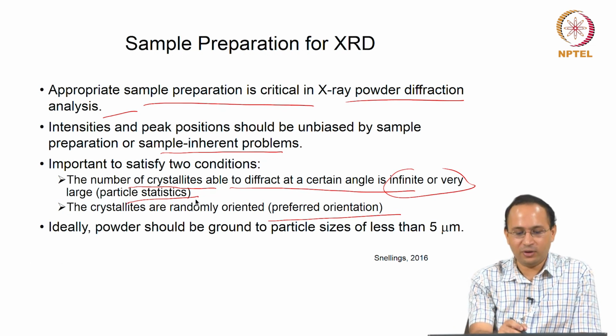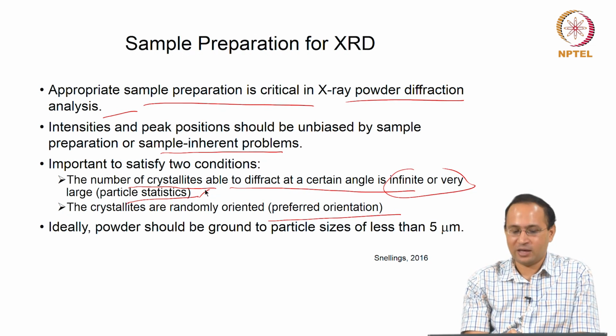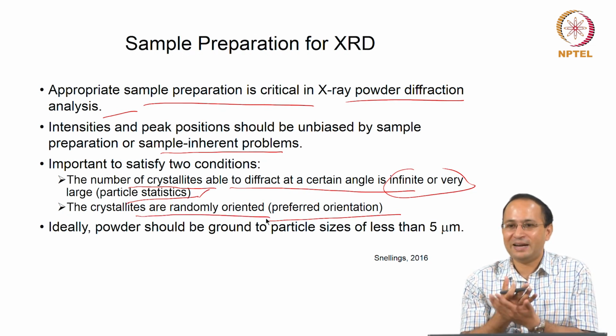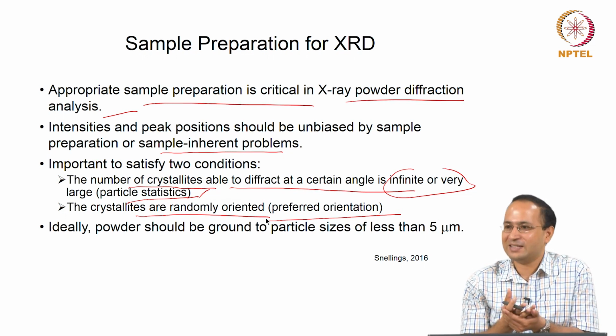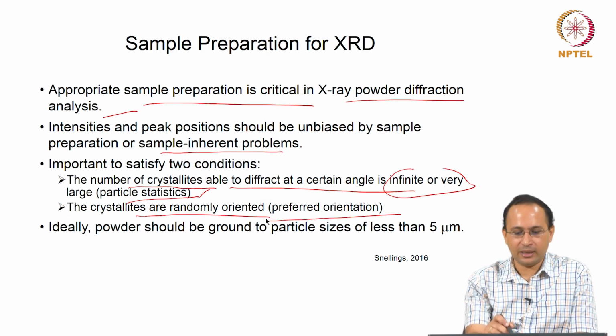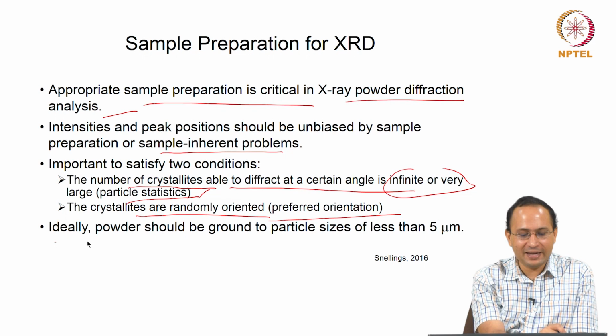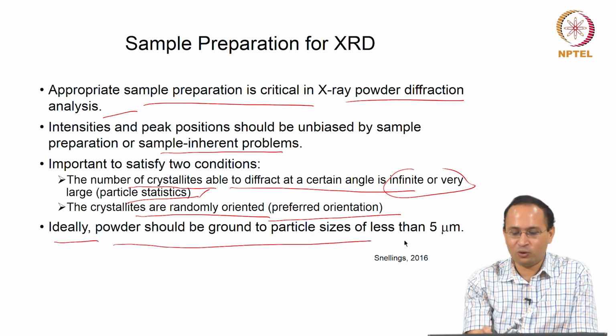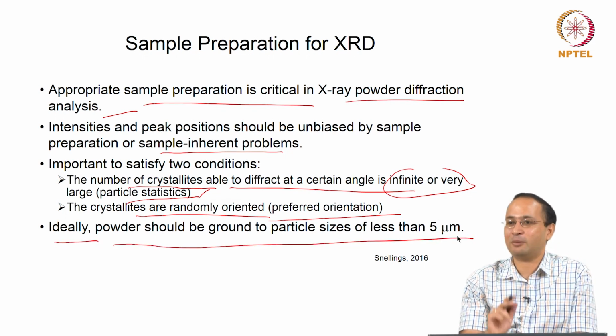So, you will deal with the particle statistics. Also you want to make sure the crystallites are randomly oriented, because you have a lot of plate-like structures, a lot of needle-like structures in your cement paste. So, you want to take care of preferred orientation. These are the two things you have to take care of. Ideally, powder should be ground to particle sizes of less than 5 micrometers.